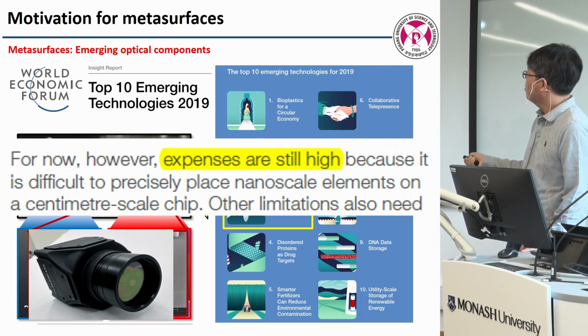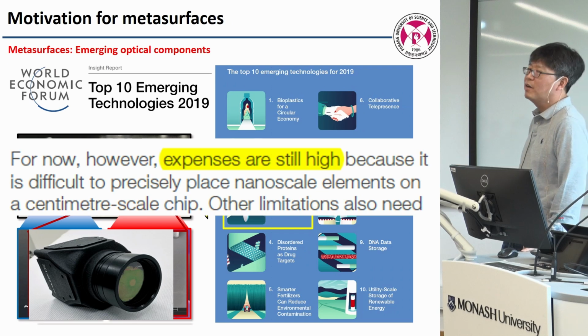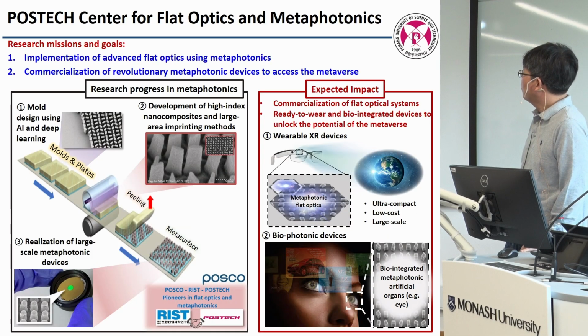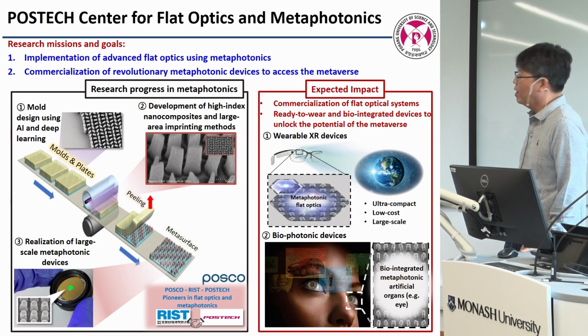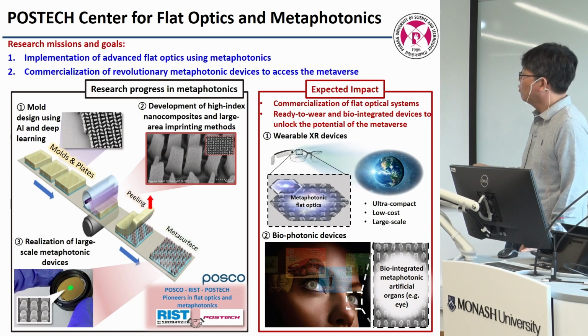It is difficult to precisely place a nanoscale element on a centimeter scale. So that was 5 years ago, but we can now do centimeter scale, even larger. So what we do in our current center in Korea, we develop some manufacturing methods and determine what is the related good material, high index, low K, and what is good for CVD, what is good for imprinting, what is good for etching, and so on.